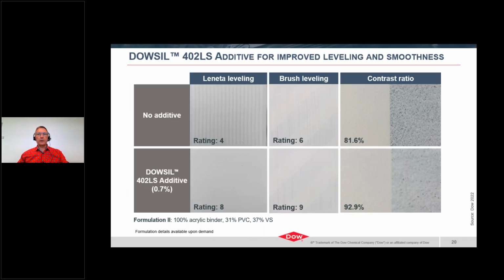Now, in this set of pictures, we can see the effect of adding the featured additive as a function of the application method, again in an acrylic-based formulation. The first column on the left corresponds to drawdown on Leneta chart using a leveling bar, and a clear difference can be observed between the control sample and the sample with the additive, resulting in a significant difference in the visual rating for the